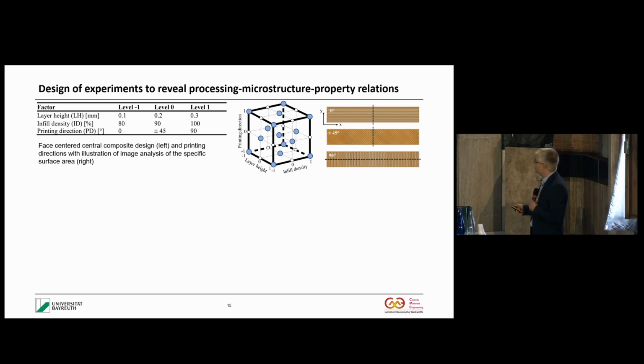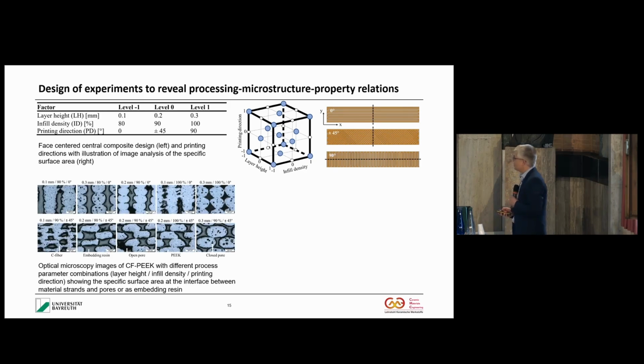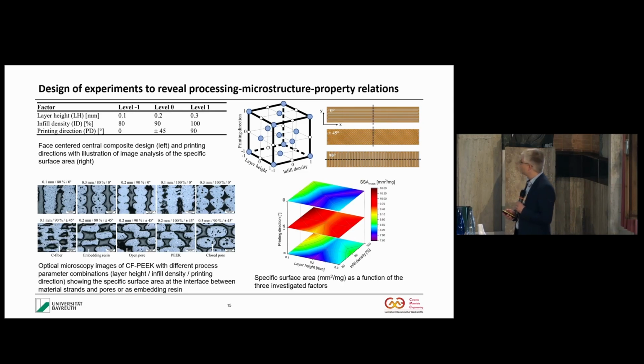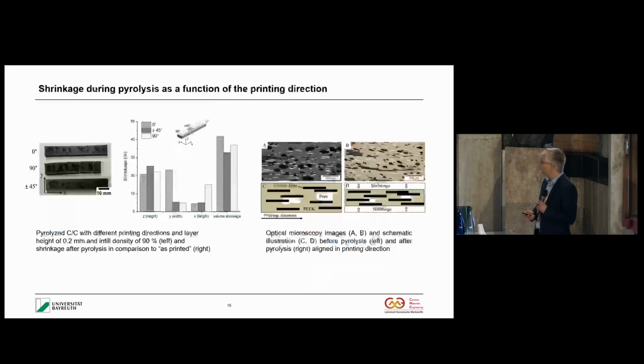Then we have the so-called infill density. That means, in the plane, how much of the area is filled in with the filaments. You have 100%, 90 and 80%, and then you have the layer height, meaning how thick one layer is. This was investigated with a statistical design. You see already the microstructure was quite different. What is also very important for the cross-linking is the internal surface area, which was also investigated, because you need an internal surface area so that the air can interact with the polymer.